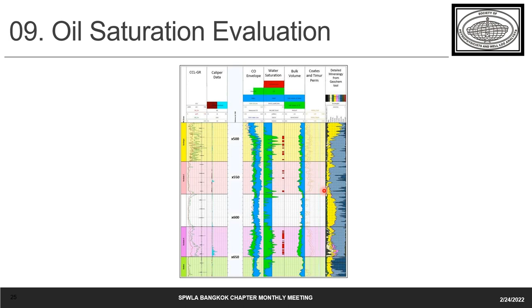So we have uranium, thorium, and potassium from the spectral gamma ray, and other elements from both inelastic and capture spectrum: silicon, calcium, magnesium, aluminium, iron, titanium, chlorine, sulfur, hydrogen, oxygen, and carbon. As you can observe in this figure, the formation is primarily limestone with some dolomites, but some shaley sand zones were also identified.